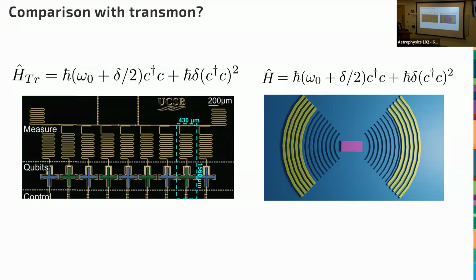Another thing is that these are really susceptible to charge noise and two-level systems that they interact with. Now, the number of two-level systems they interact with is proportional to basically how much area they take up. Ours take up an area that is fully like 10 to the 4 squared times smaller. And so the total number of two-level systems that this thing will interact with at the same frequency is a huge order of magnitude, like 8 orders of magnitude smaller. So potentially, the decoherence mechanisms might be better for a system that is intrinsically smaller.